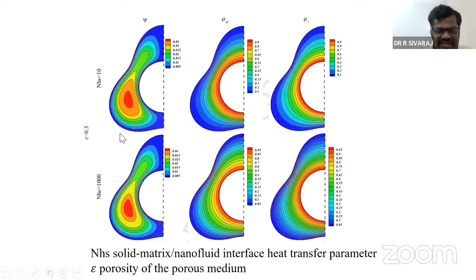From the results, we understand that here the parameter epsilon stands for the porosity of the porous medium, which is fixed at 0.3. Then the NHS is the solid matrix or nanofluid interface heat transfer parameter. When this parameter is increased from 10 to 1000, in the fluid flow through streamlines we can see there is a decrease in the hot region. The size of this is being reduced, meaning the fluid flow is getting reduced at this location.